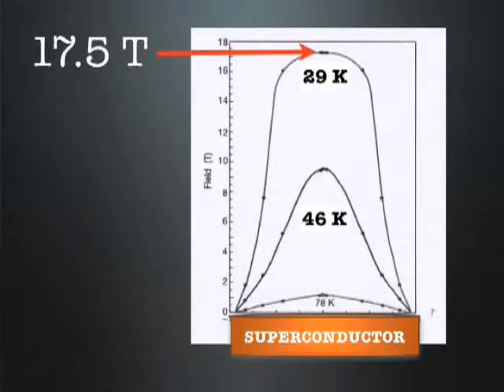The world record trap field is 17 Tesla at 29 Kelvin, which is pretty amazing. If you look at the amount of energy in there, it's more than 100 times the energy density of ferromagnetic iron, fully magnetized, which is the greatest or strongest ferromagnet that we know. So we can make these very large magnetic fields in samples of a given size.